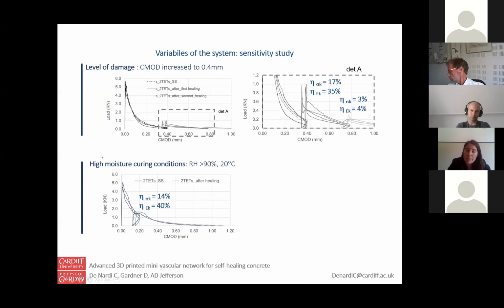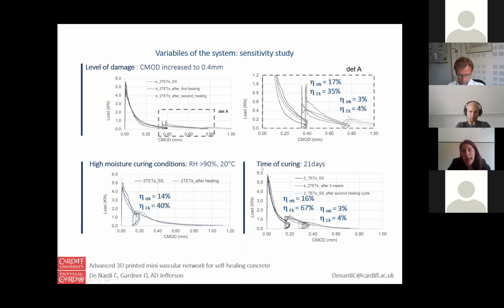However, when we just add an extra amount of water to the reaction between the sodium silicate and the calcium hydroxide present in the matrix, it seems to slightly affect the healing efficacy, for both the strength and the stiffness. And when we prolong the time of the healing, it is actually of limited benefit.